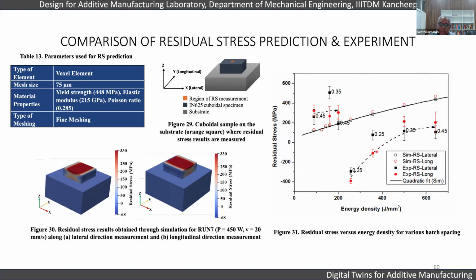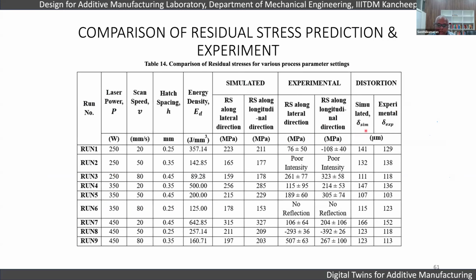We found that the results are not matching. For example, comparing the experimentally measured residual stresses using XRD with the simulated residual stresses along the lateral and long directions, there's a huge difference. I'll show the difference in the table here. Here you can see the experimental and simulated values. In some cases, for run 4, you can see there's a drastic change. Somewhere the simulated distortions are matching, but some parts are very difficult to get measured residuals.